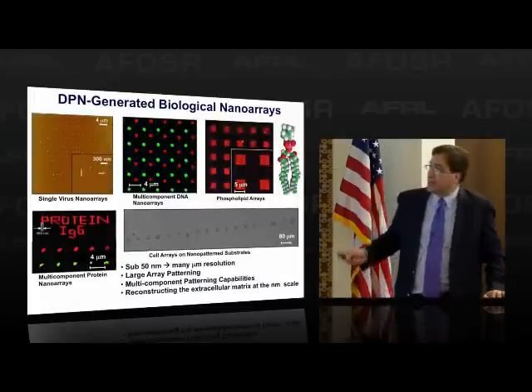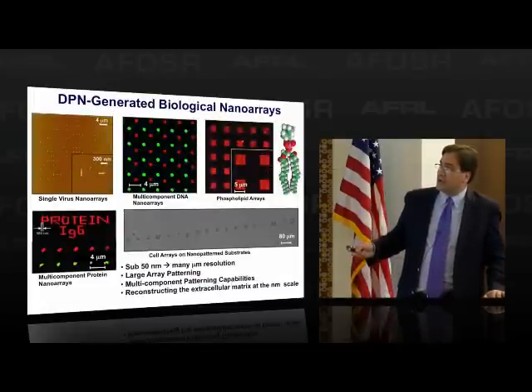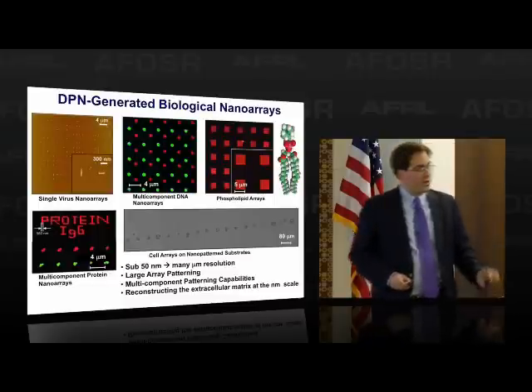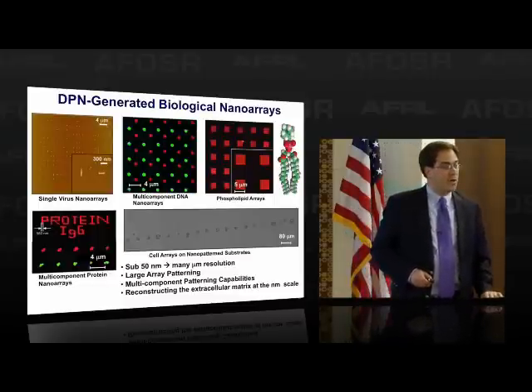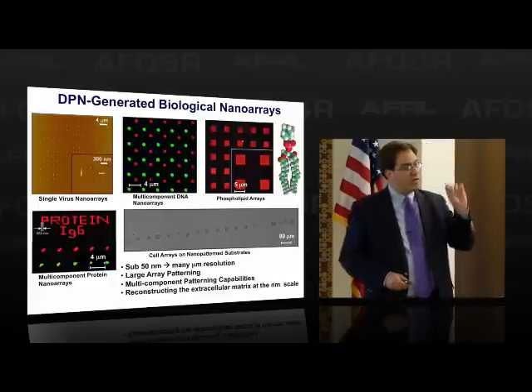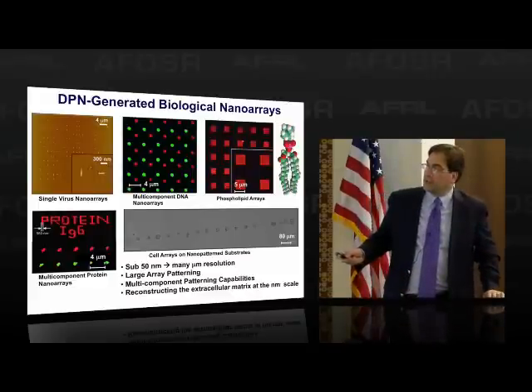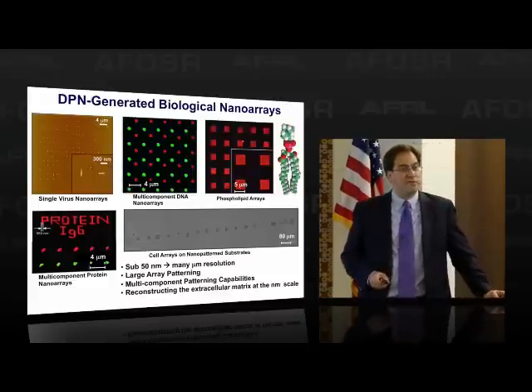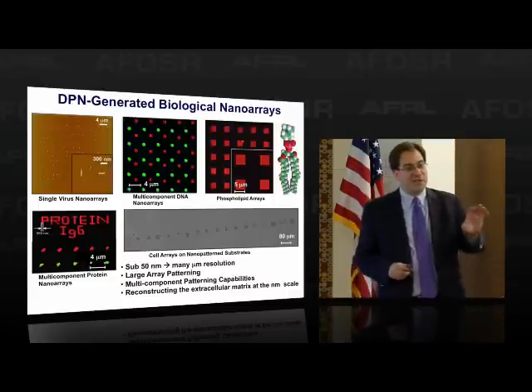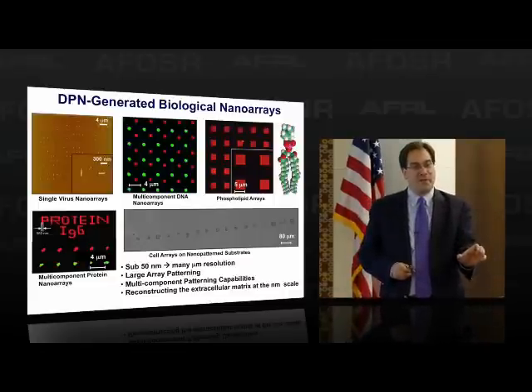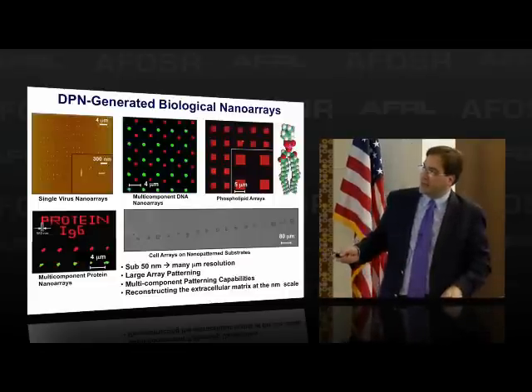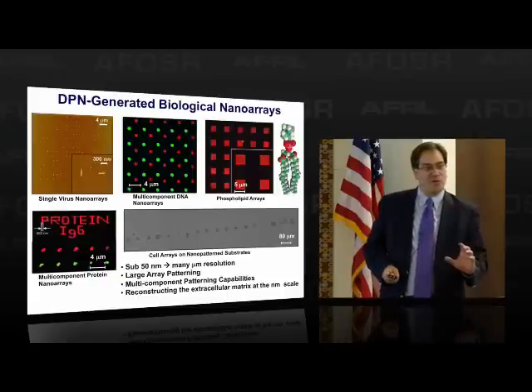So here's some examples of this. This is a tobacco mosaic virus array here. You can see it's a perpendicular array where we've put down molecules, actually carboxylic acid terminated monolayers, that we coordinate zinc to, and the zinc coordinates then to the carboxylate-rich surface of the virus. And so the virus adheres to each spot that we've made by DiP-Pen, but we've made, in this case, a perpendicular array, so we're controlling the orientation.